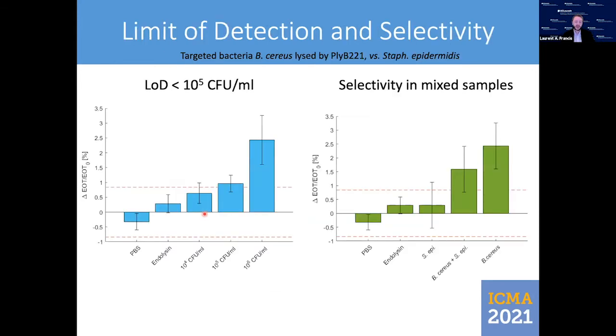I come back to the slide here. We see different effects. The first thing is that we have an error range which is fairly large. Thus, we need to have about 1% of change in order to be sure to be out of the signal error. And the second point, not seen in the graph here, we have shift over time because the saline solution is etching slowly our silicon oxide material, and thus will have a shift over time. And the shift is, of course, a problem because it will induce false detection.